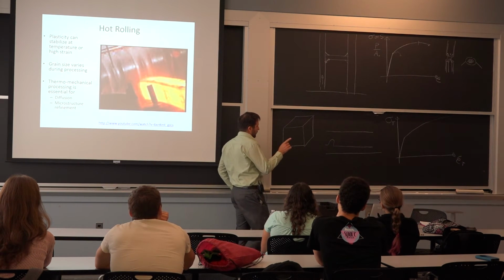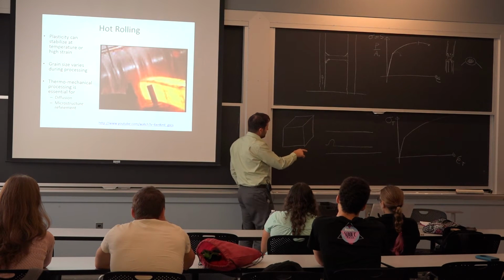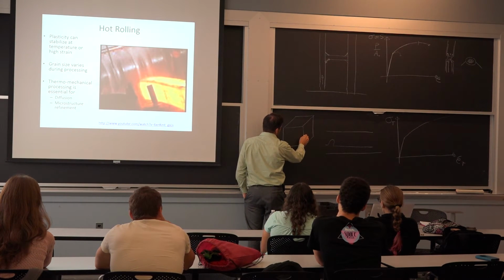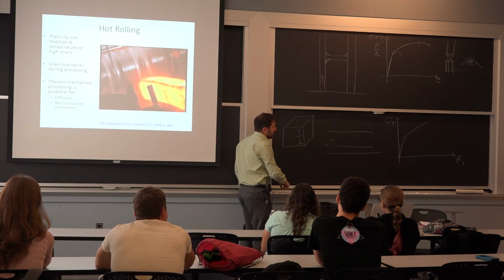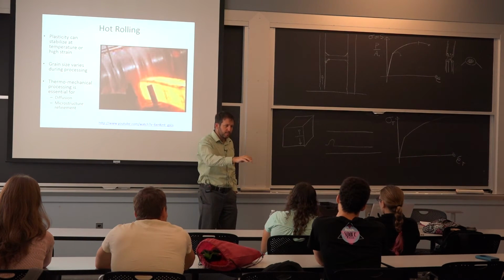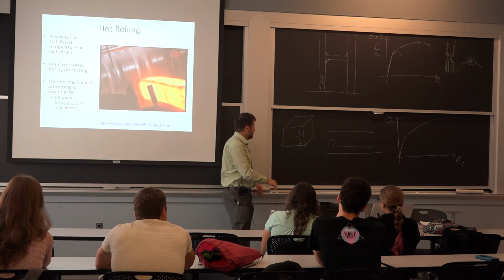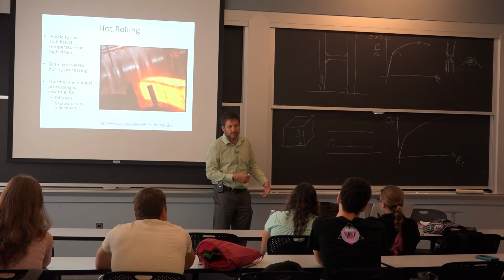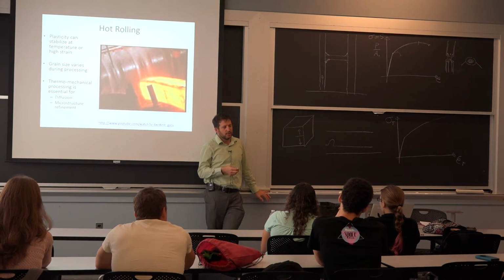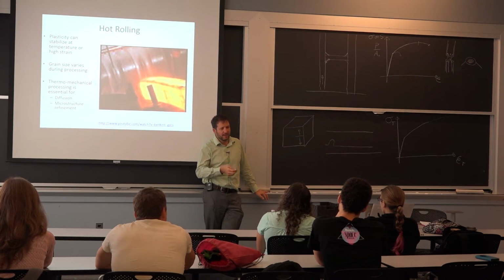Now, as a result of the inclusions in aluminum, if I'm looking for the fracture toughness, so say I make a pre-notch here and I pull on it, if this plane of the crack is the rolling plane, my fracture toughness can be at most half, just half or less than half what it would be if I do it transverse to the rolling direction. And it's not so much the yield strength and the grain elongation. No. It is the inclusions. So it does play a big role.